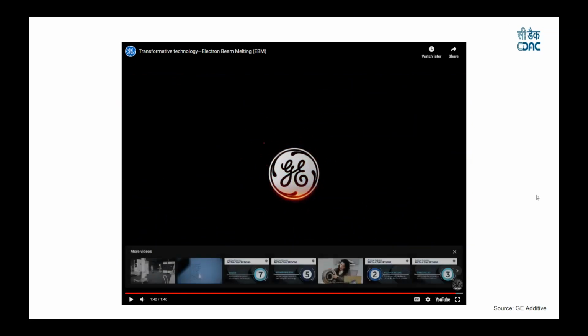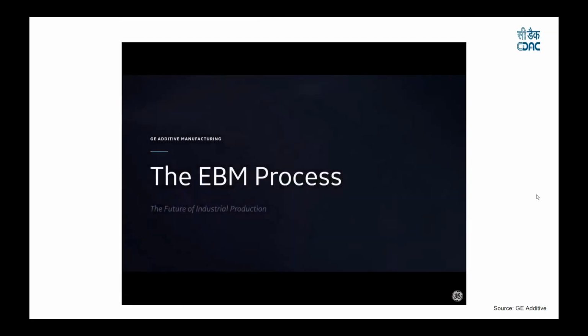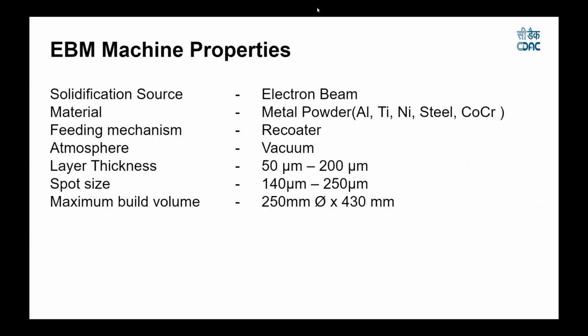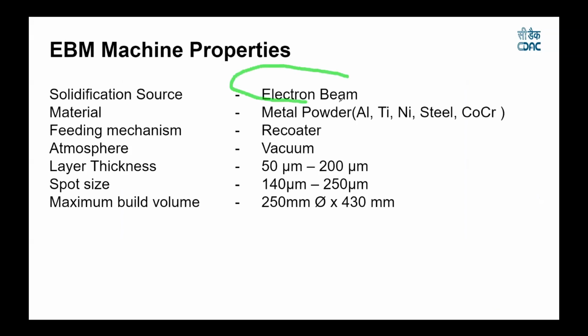So that's how the EBM process works, which is similar to the SLM process. So coming to the specifications of the machine. Here we are using an electron beam as a solidification source. In case of SLM, we use the laser as a solidification source. The materials are similar to the SLM process, and the feeding mechanism is a recoater. For the atmosphere, there we used inert gas. Here we are going to use vacuum.